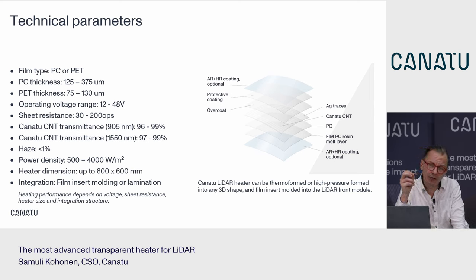And to give you a bit of an idea about transmittance, what we can provide in LiDAR applications. On 905 nanometer LiDARs, typical transmittance is somewhere between 96 to 99%. And if we are talking about 1550 nanometer LiDARs, it is slightly higher, going up to 99%. Of course, the values I'm presenting here are substrate normalized values. So our CNT layer is creating roughly 1 to 4% transmittance loss in your application.